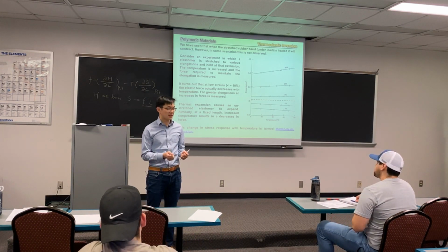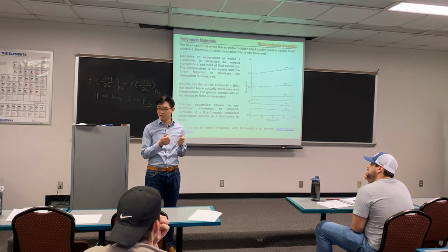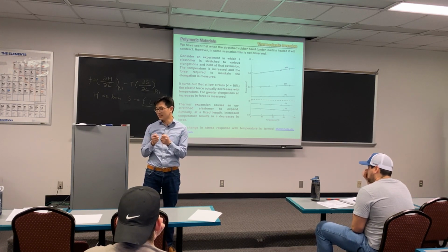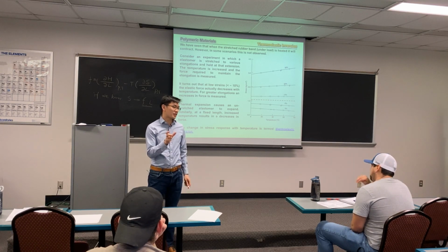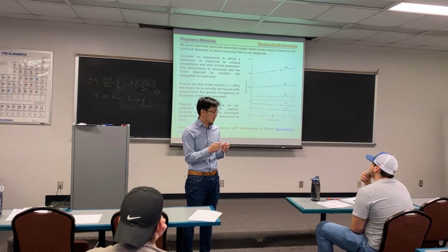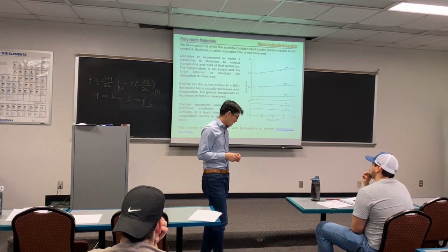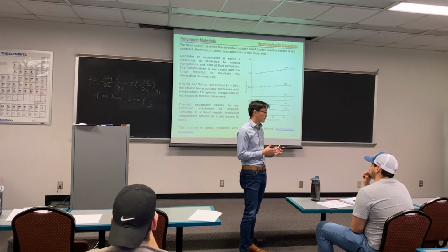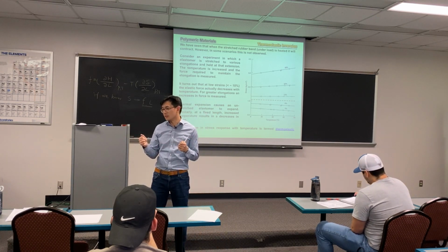So what you typically do is hold a rubber band in your hand and stretch it very rapidly, and there's a change in temperature in the rubber band. When you deform it, the rubber band will lose entropy, so it will need to give out some form of work to the environment. So it will give out heat, actually.